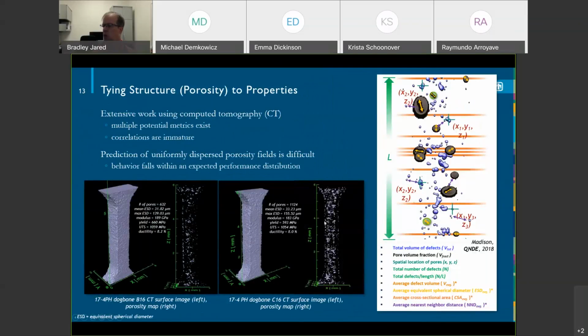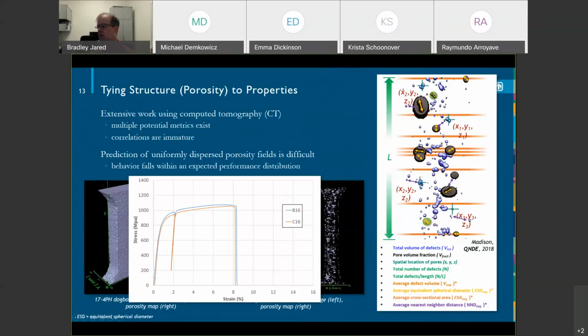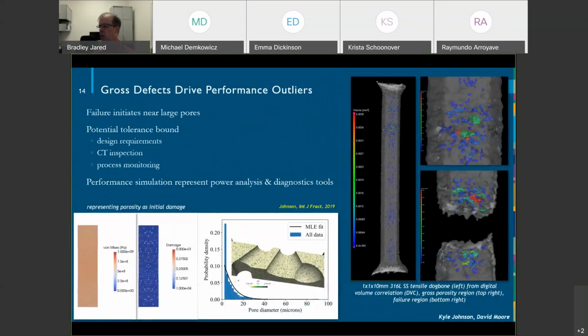If you look at that slide I showed a second ago, it's kind of hard to say, well, there's a worse pore in here, right? It's hard to say there's a really large pore. There's sort of a pore field that's sort of uniform, right? When you see that, you start seeing behavior that looks fairly consistent in a lot of these cases. And what we found is that if we have these large pores, so this is pore size, and you see this red one, and it's really close to where this localized necking and failure occurs in this 316 part, you can start saying something about quality.